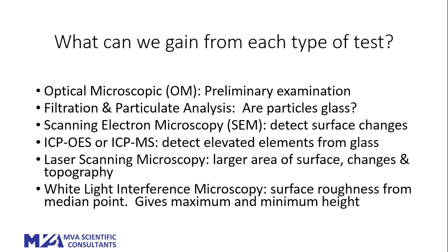With optical microscopy, it's good to start at low magnification to get an overview of what the whole vial looks like, identify which areas might be more suspect, and map out regions of interest for further investigation. For filtration and particulate analysis, the key question in a delamination issue is whether the particles isolated from the product are actually glass or some other foreign material that shouldn't be in the product.